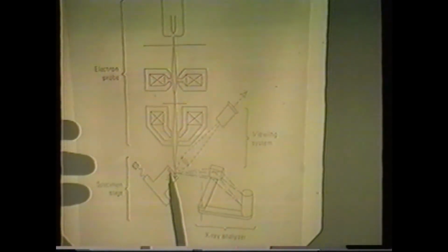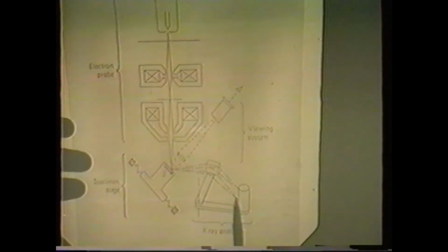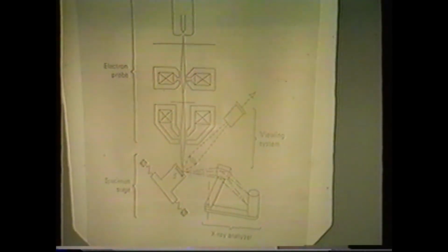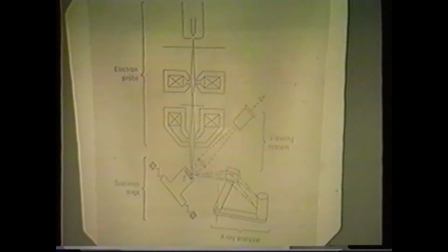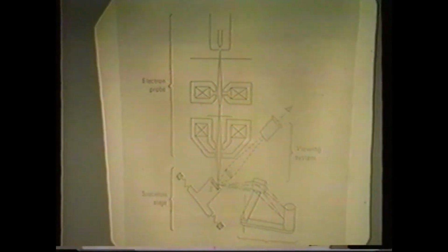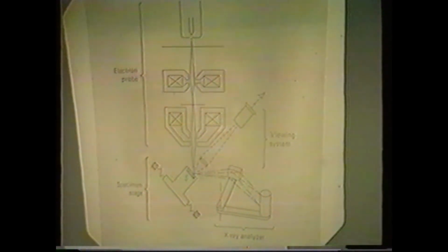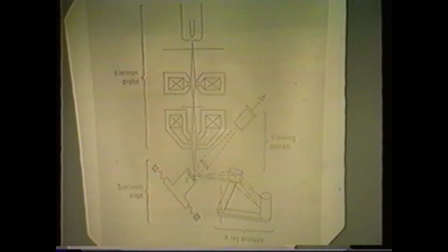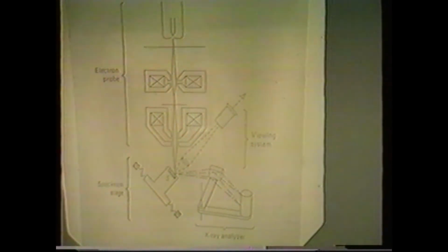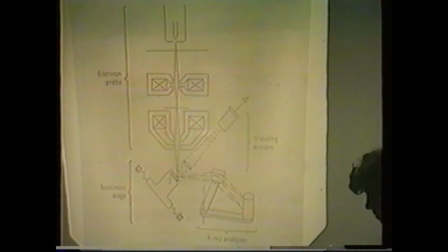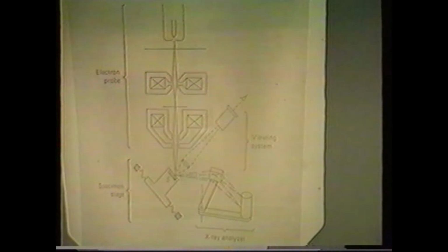The fluorescence is then emitted and basically detected through an X-ray analyzer. In this case, we use an energy dispersive X-ray analyzer as opposed to a monochromator-based system because it has basically 100-fold sensitivity over a monochromator-based system. So this was the way we uniquely identified these pigments.